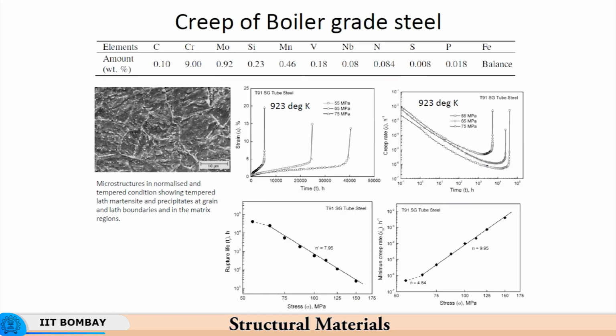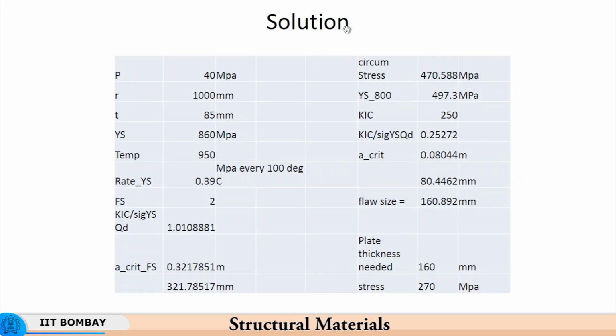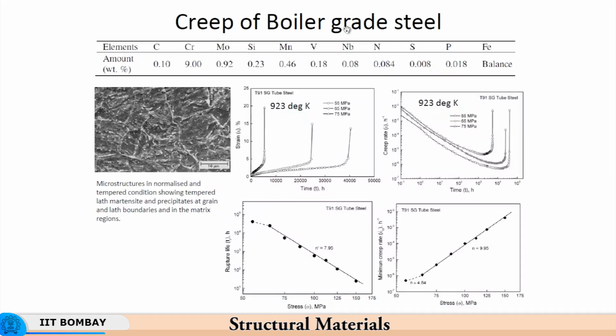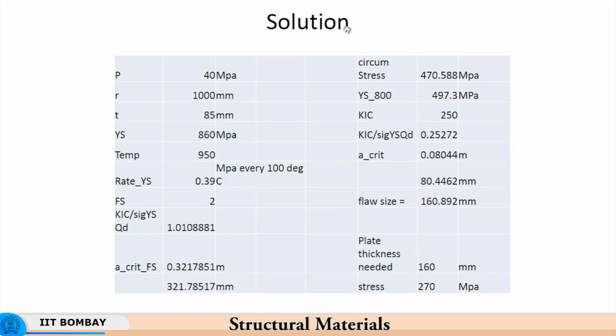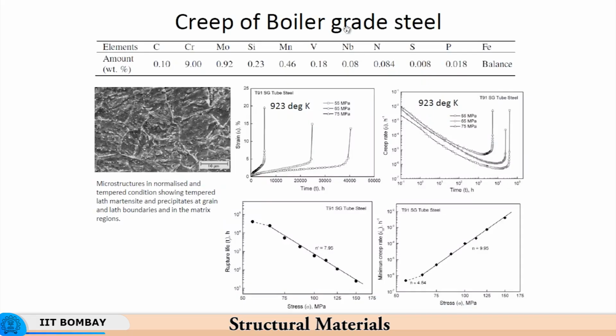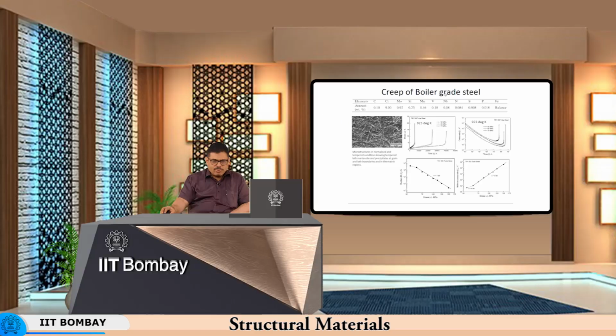And now, boiler is an item that has to go on for years together. So, once you have a boiler running, it has to go on for years together. So, that is the reason why this design, although it is okay for yield, it is not okay from the creep point of view. So, we need to consider creep and creep strain as a criterion for failure, and increase the thickness further to minimize the stress, or bring the stress to below, let us say 55 MPa or so. Now, 55 MPa is a ridiculously low stress for a material that will yield at something like 860 MPa at room temperature, but yes, it has to be that low in order to prevent significant amount of creep.